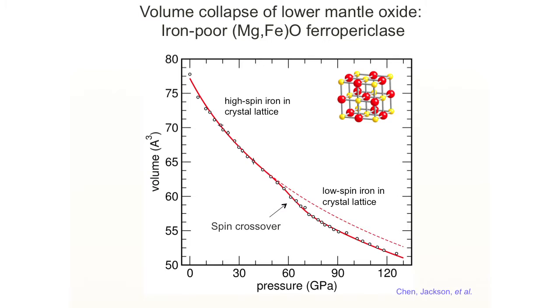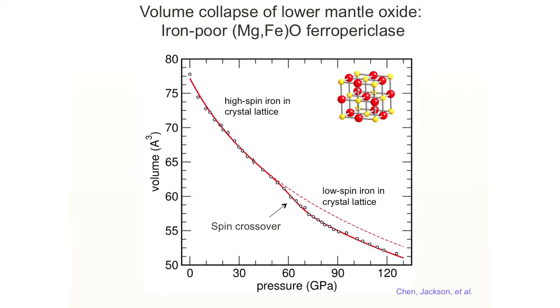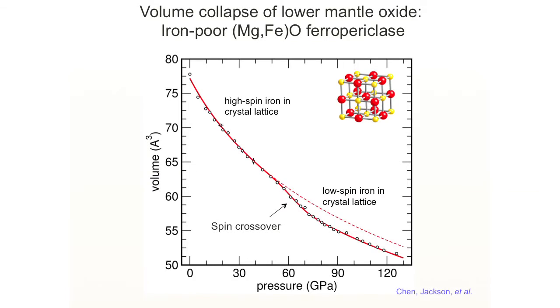As we increase the pressure, we see a deviation from this dashed line, which was thought to be how this material behaved about 10 or 20 years ago. So in this vicinity, the material, which is this iron-bearing oxide, those iron atoms that are sitting in the lattice undergo what's called a spin crossover. Their spins in their outer D shell become paired at high pressure. And in that process, it undergoes a volume collapse. So that makes it a lot denser than what we would have thought originally.